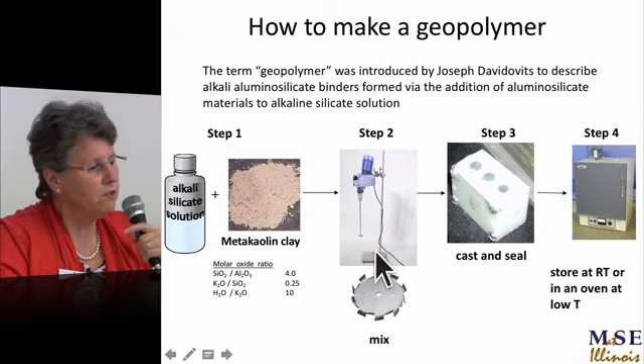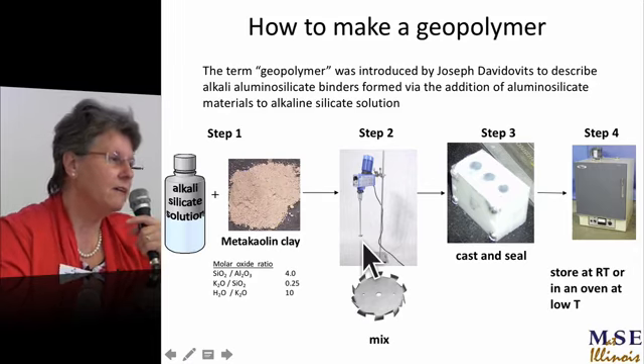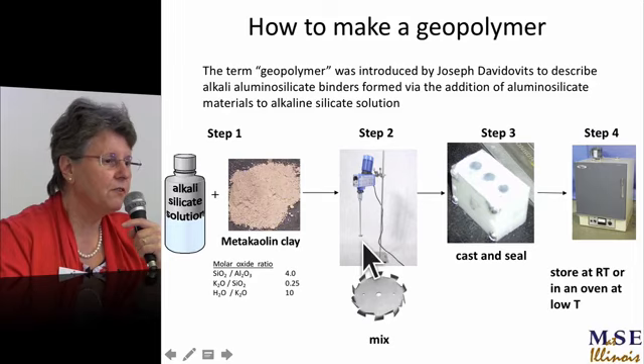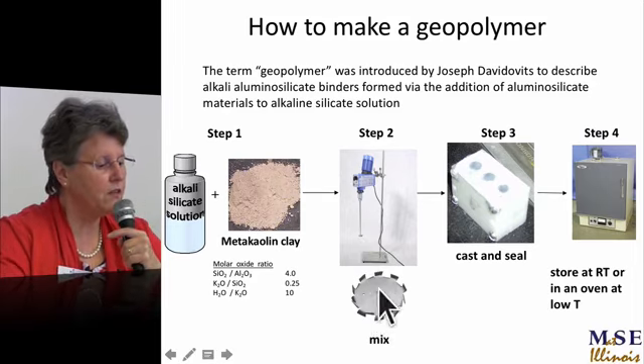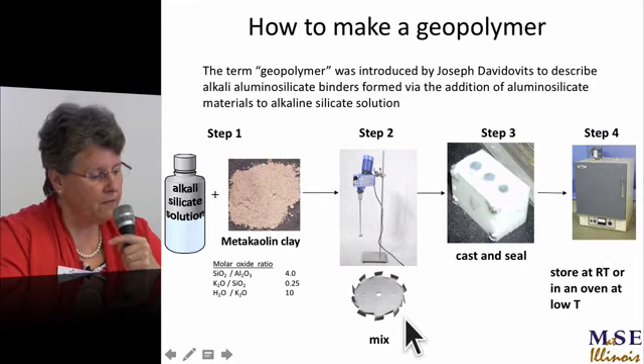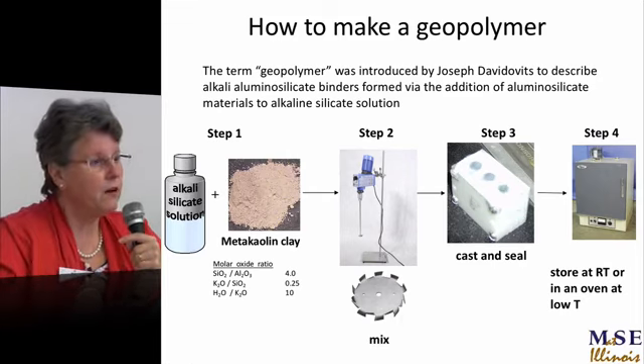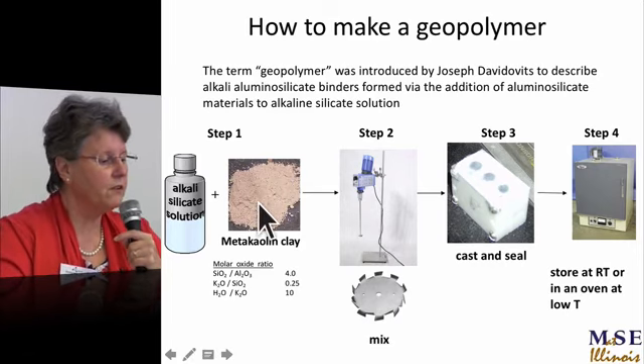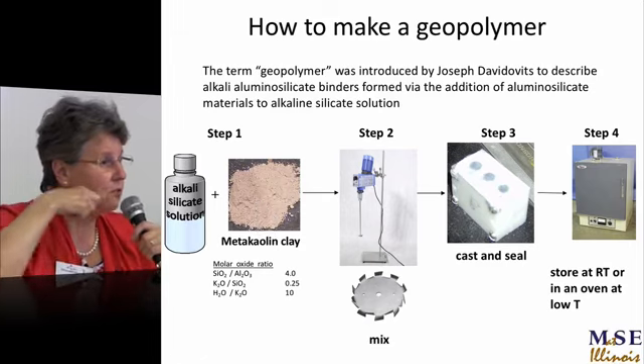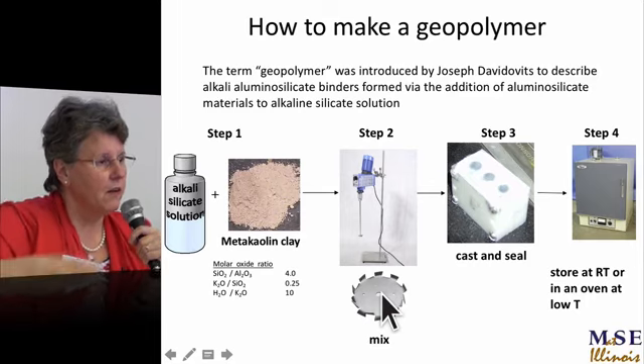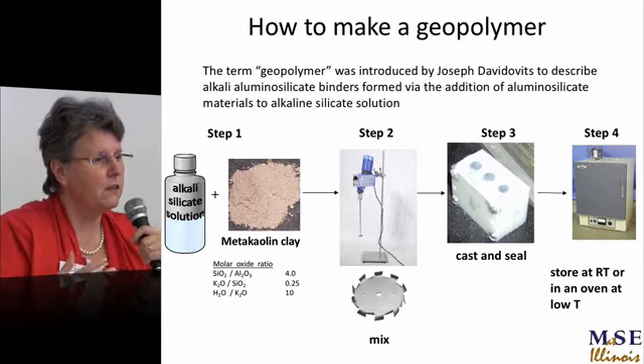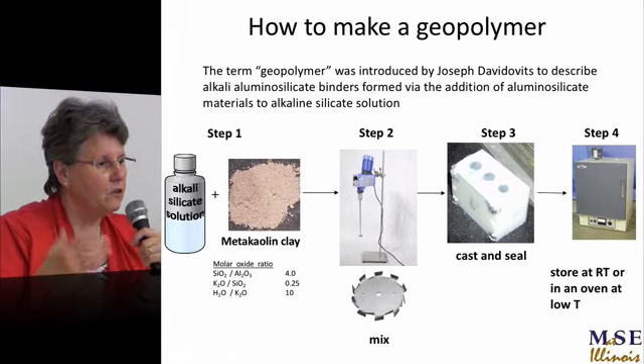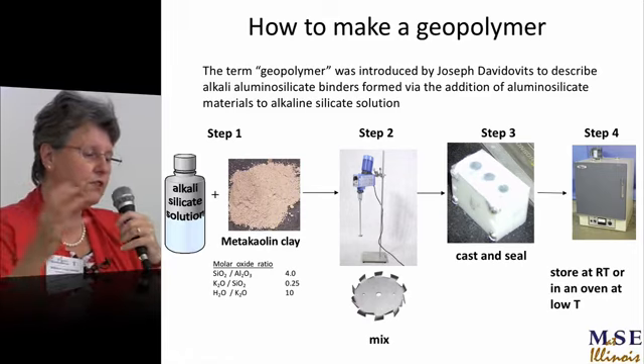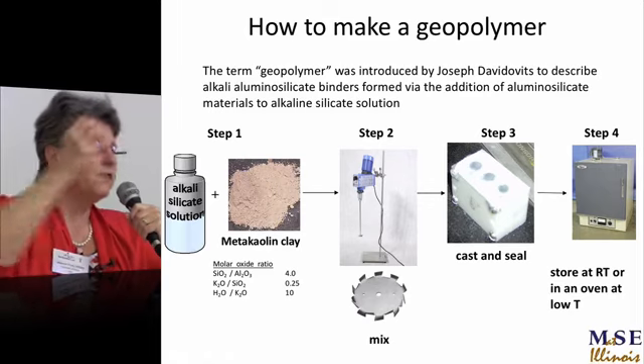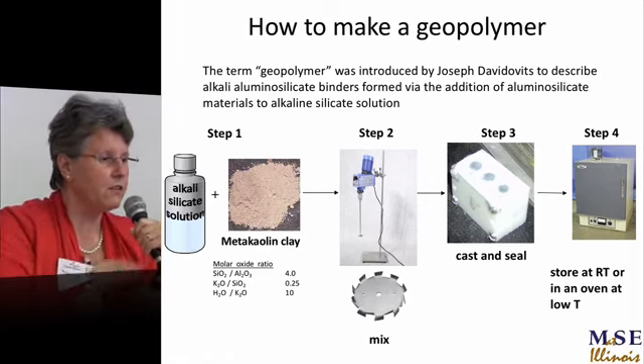The first year, we used a milkshake mixer with a little propeller, and we had a lot of unreacted phase, only 50% reacted. And then with a high shear mixing paddle with teeth up, teeth down, teeth up, teeth down, we use this. And that makes the rheology good. First, you get the powder and the liquid, and you get the texture of toothpaste. But when you put it in a high shear mixer, it becomes low viscosity, like runny honey in summer. So that's the trick. As soon as you attack the metakaolin, you have to clean off what you've formed so you keep the reaction going. You need the high shear mixer.